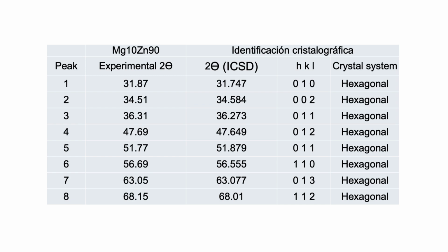Moreover, the most significant variation in the crystallographic planes is in plane 002, at the 2θ angle, and it is here where we can indicate a displacement in the diffraction peak related to plane 002, as we can see in the figure of the results of the XRD study. The effect of the peak shift is displayed in the residual stress, which will be discussed later.